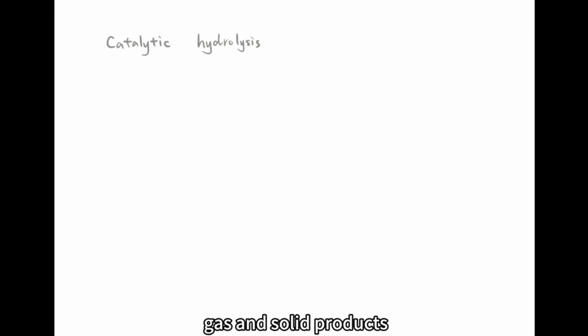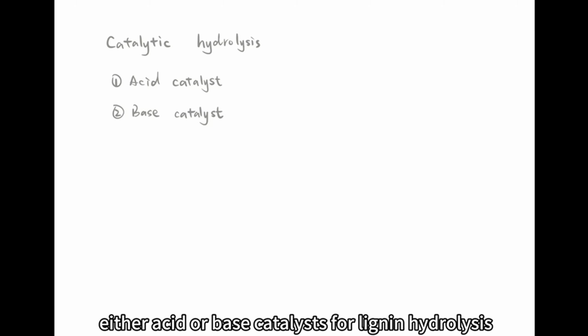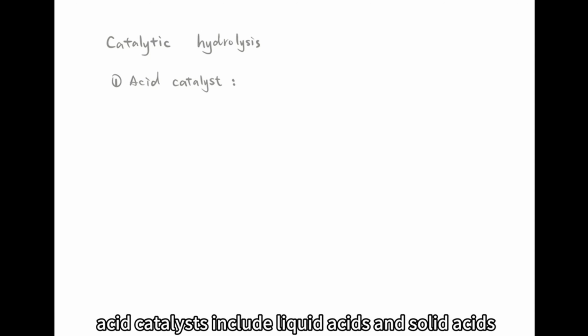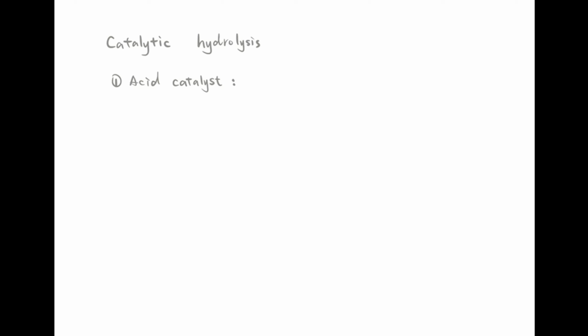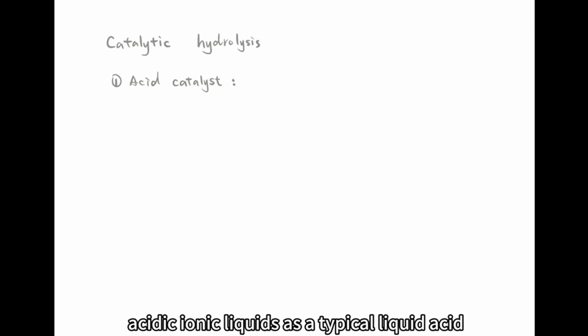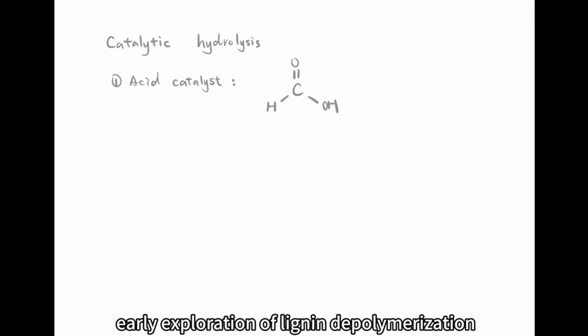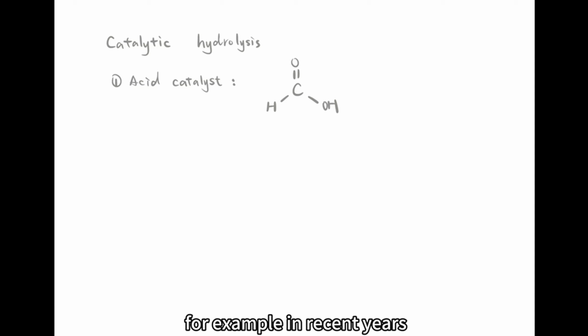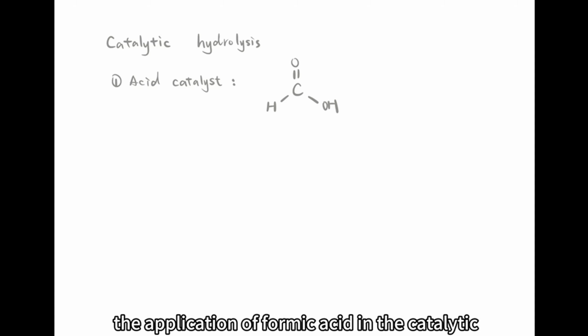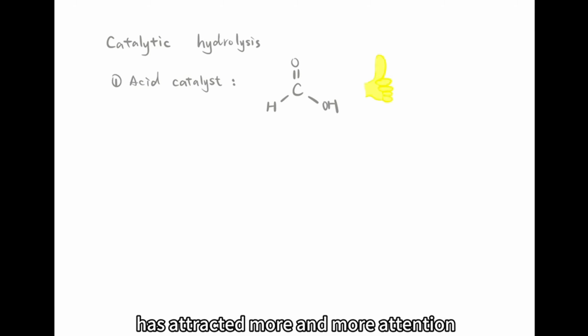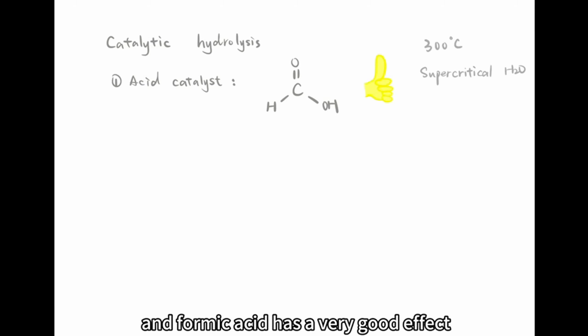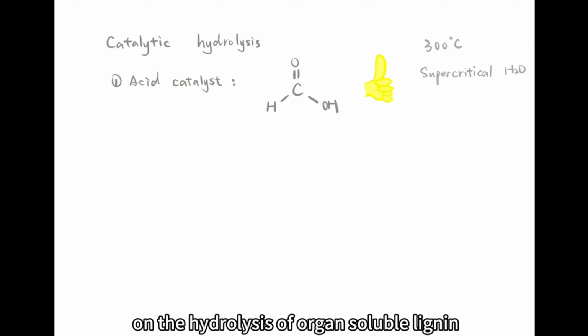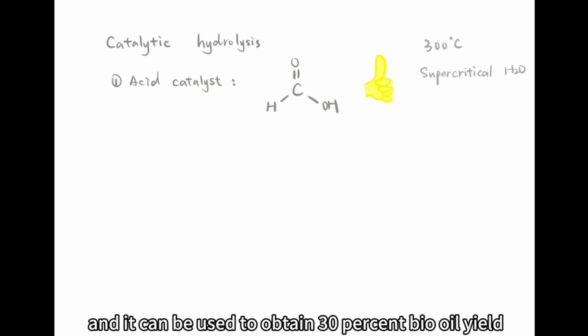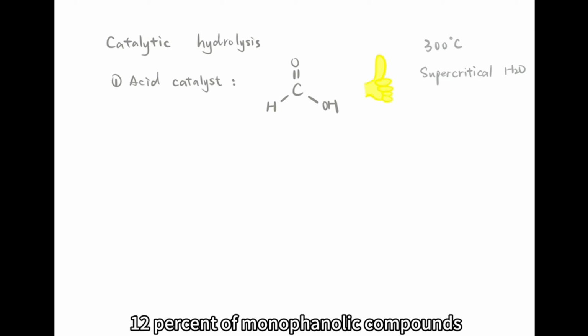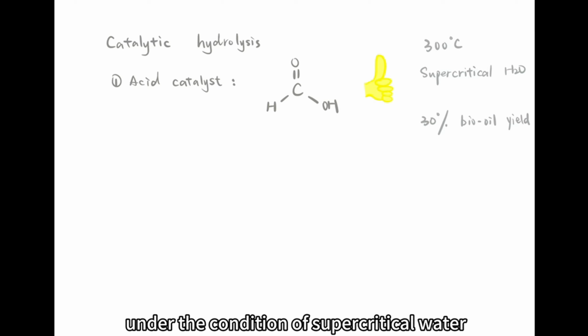At the end of the reaction, the products of catalytic thermal cracking of lignin are separated to obtain liquid, gas, and solid products. Catalytic hydrolysis uses either acid or base catalysts for lignin hydrolysis. Morphologically, acid catalysts include liquid acids and solid acids. Acidic ionic liquids, as a typical liquid acid, were widely used in the early exploration of lignin depolymerization. For example, in recent years, the application of formic acid in the catalytic hydrolysis of lignin has attracted more and more attention, and formic acid has a very good effect on the hydrolysis of organosolv lignin.